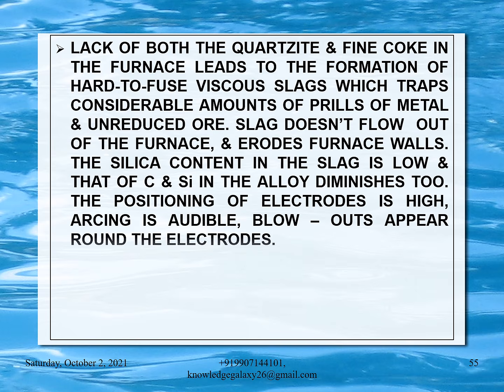Lack of both the quartzite and fine coke in the furnace leads to the formation of hard-to-fuse viscous slags, which trap considerable amounts of prills of metal and unreduced ore. Slag doesn't flow out of the furnace and erodes furnace walls. The silica content in the slag is low, and that of carbon and silicon in the alloy diminishes too.